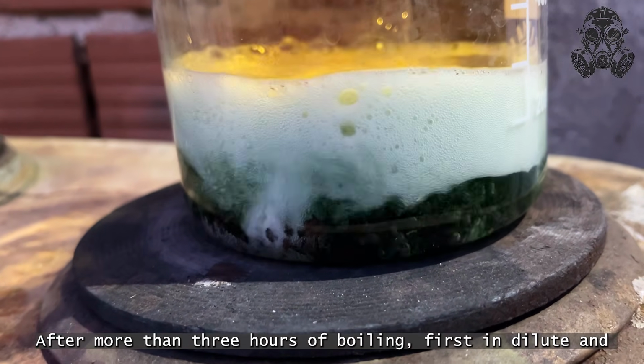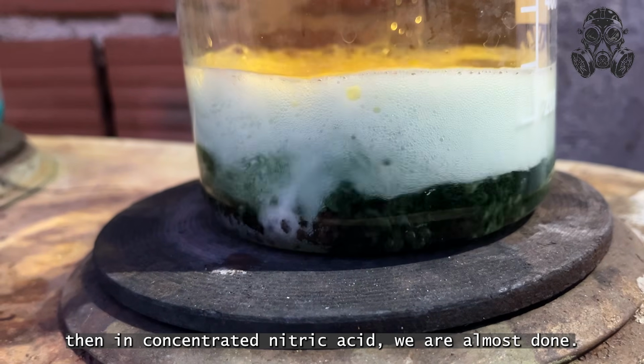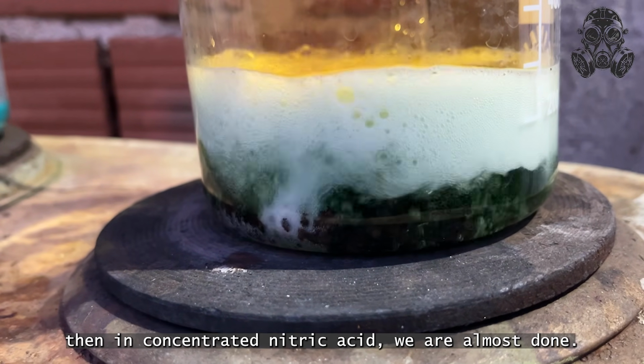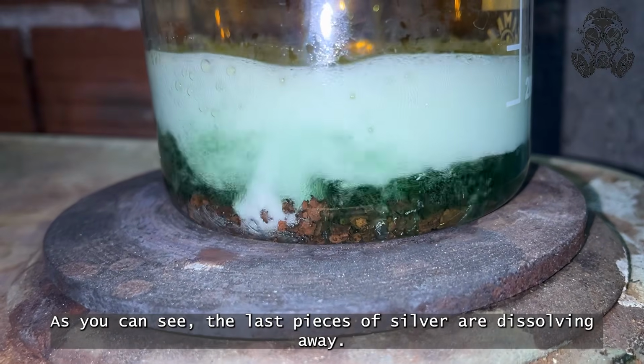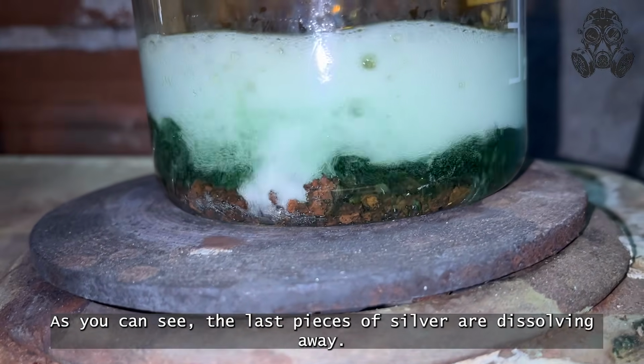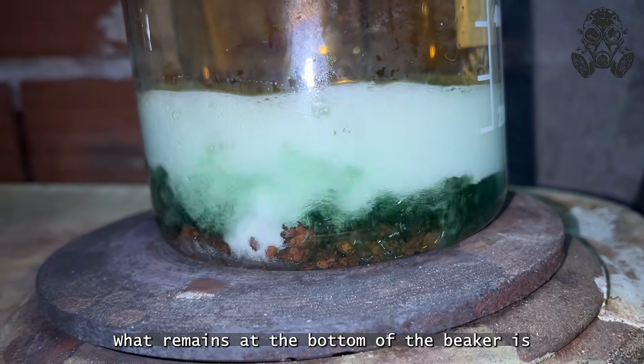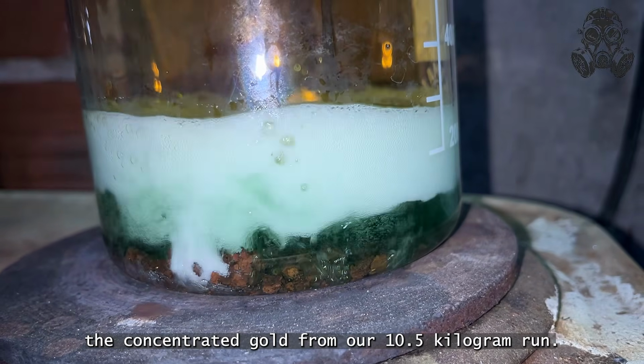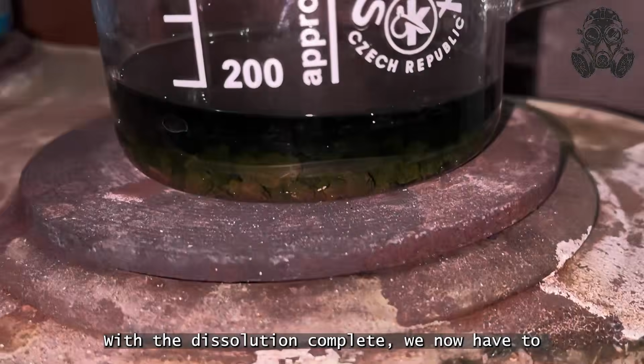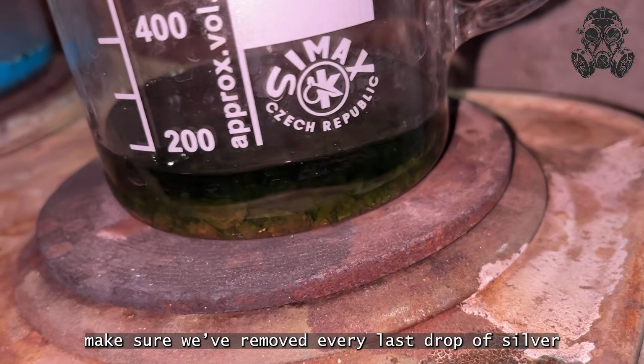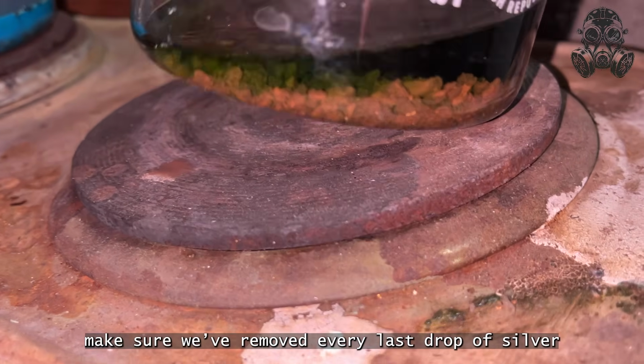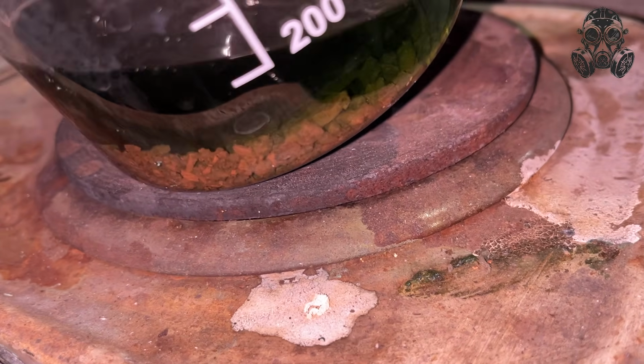After more than 3 hours of boiling, first in dilute and then in concentrated nitric acid, we are almost done. As you can see, the last pieces of silver are dissolving away. What remains at the bottom of the beaker is the concentrated gold from our 10.5 kilogram run. With the dissolution complete, we now have to make sure we've removed every last drop of silver nitrate from our gold mud.